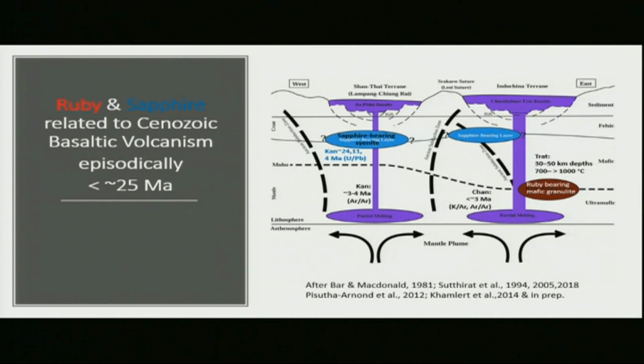In Kanchanaburi, they have done a lot of study on this. They found that the sapphire in Kanchanaburi is associated with what they call syenite or syenitic rocks. That's the precursor, the protolith of the sapphire over there. And it formed at a very shallow level, probably in the middle or lower crust. And there's been some dating on the zircon inclusions in the sapphire, and it was found that they can be dated at 24, 11, or 4 million years ago. And then there was a basaltic magma underneath, dated about 3 to 4 million years younger, and then it erupted and passed through this sapphire-bearing layer and brought the sapphire up to the surface in Kanchanaburi or Bo Phloi areas, before it was eroded and then deposited into the gravel bed. That's the idea that we understand.